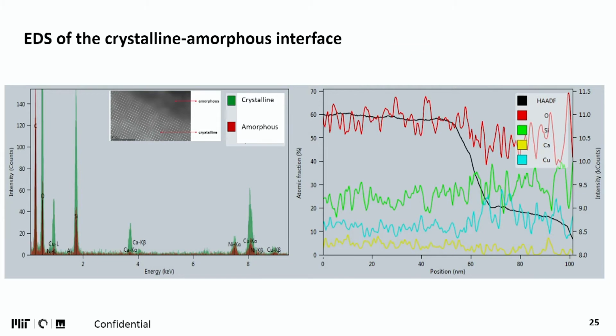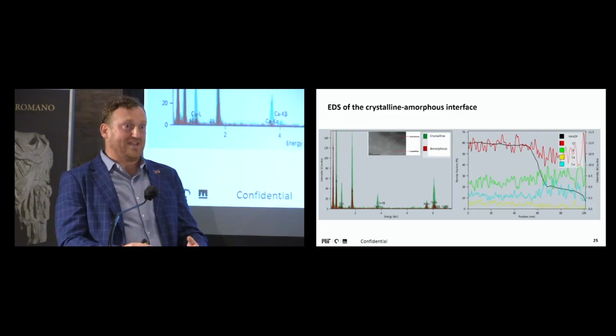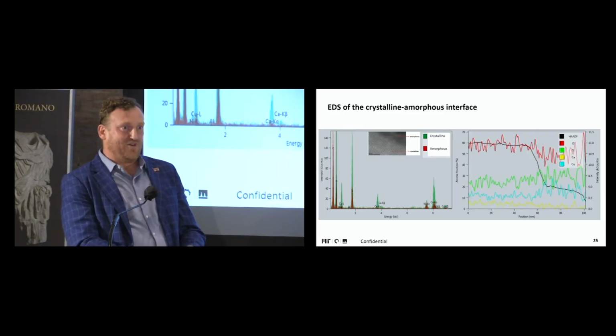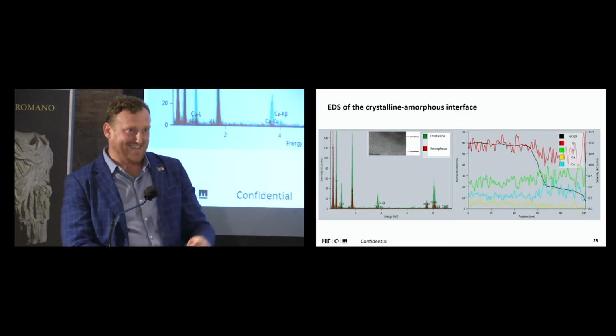And these are very encouraging results, and this basically shows constant concentration of calcium, silicon, copper, and oxygen in the Egyptian blue crystal. Of course, you see the atoms, they are perfect, but then it starts to oscillate in the amorphous part, which eventually now is a matter of putting good students to work and having great samples to actually see the differences in the amorphous phase, because this is the one that we would like to focus on eventually, to be able to see what was expelled. So what was the original composition that was melting in that kiln?